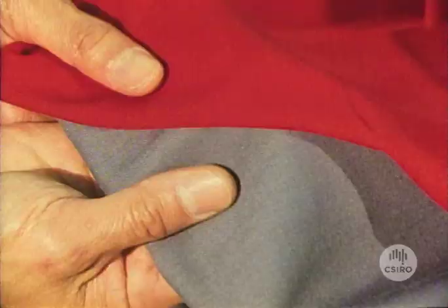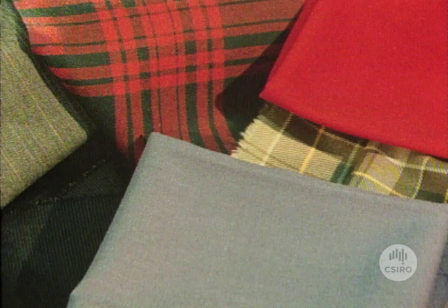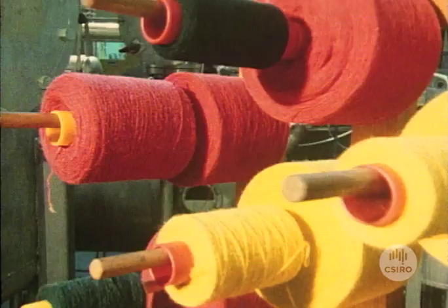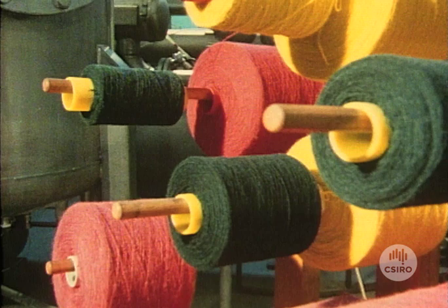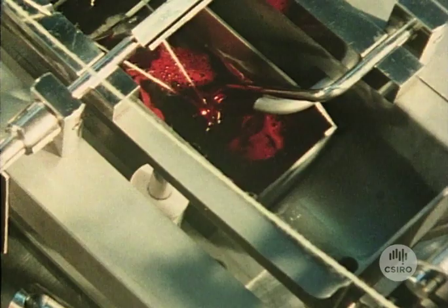The savings of the Sirospun process have made it economical for many manufacturers to produce a range of fabrics. Unlike worsteds, woolen yarns are designed to remain fluffy. Dyeing these yarns can take up to two hours of boiling in large vats. But this radical prototype machine can achieve a similar result in less than ten minutes — it continuously dyes a single thread of yarn at between 300 and 600 meters per minute.